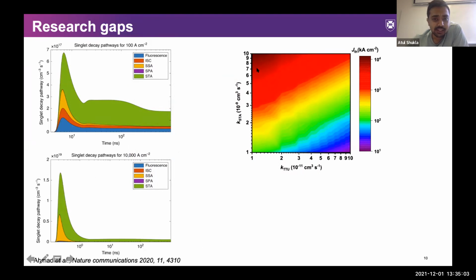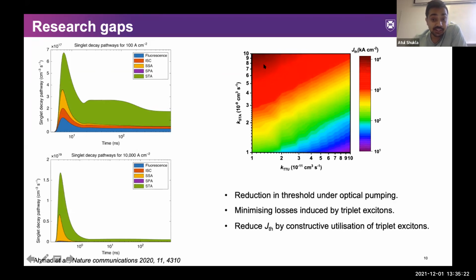And this can also be seen from the current density thresholds becoming really high as the STA is higher. So in order to get close to electrically pumped lasers in longer wavelength emitting materials, we firstly need to reduce the thresholds, and also minimize the losses due to triplet excitons, and also get a positive contribution from these triplet excitons so as to reduce the current densities further. And the last two points here mainly deal with managing the triplet excitons judiciously in order to get good performance.